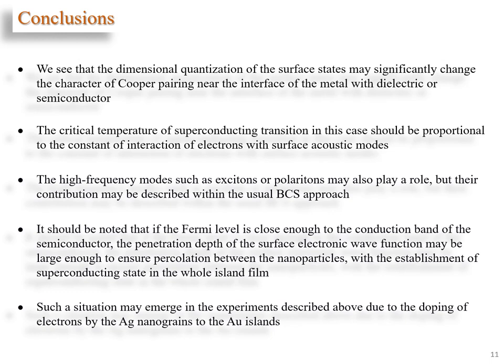It should be noted that if the Fermi level is close enough to the conduction band of the semiconductor, the penetration depth of the surface electronic wave function may be large enough to ensure percolation between the nanoparticles, with the establishment of superconducting state in the whole island film. Such a situation may emerge in the experiments described above, due to the doping of electrons by the silver nanograins to the gold islands.